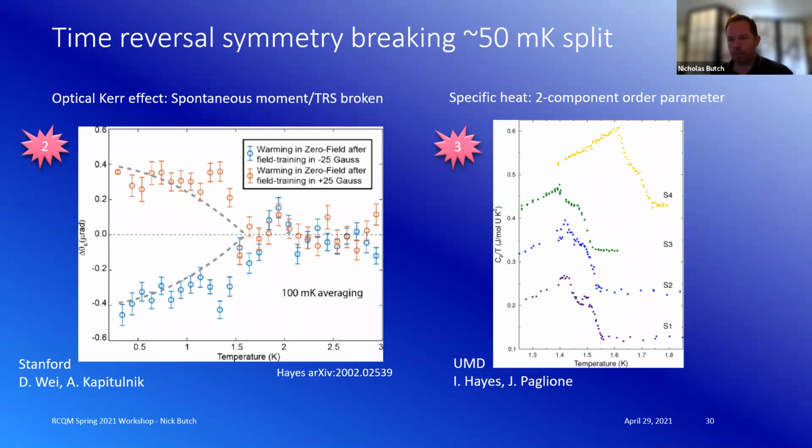And I showed you earlier a single jump in the specific heat, but if you do a more careful experiment, that is, smaller temperature steps, for example, in your calorimetry, you'll find what we're showing here on the right, which is that there are actually always 2 jumps. So this jump actually is really 2 transitions. And I'll talk a little bit about that in the next couple slides.